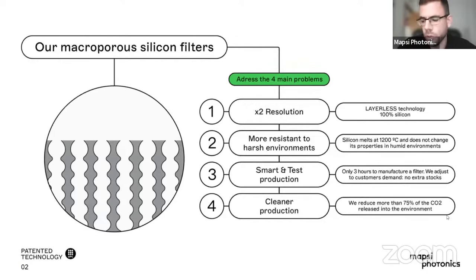Of course, we can produce a little bit lower, but in here, like in 4 microns, our characteristics are quite similar to the ones of the competition. But as we are using silicon, and we are an all-silicon platform, we are very resistant to harsh environments, at high temperature environments as well as high humidity environments. We don't feel the difference since the silicon melts at 1,200 degrees. We can suffer a lot of different high temperatures.